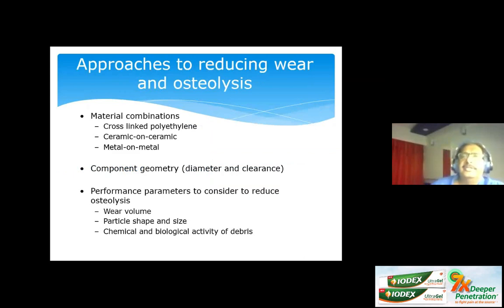So what are the approaches that we can use to reduce the wear and the osteolysis? First of all is the material combinations, whether we use cross-linked polyethylene, whether we use ceramic on ceramic. And earlier, that was also the rationale for metal on metal, which of course now has been put on the back burner for various reasons. Component geometry, in fact, which refers to diameter of the head and clearance, is important, and we will touch on that in a minute. Performance parameters that we consider to reduce osteolysis is the volume of wear, the size and shape of the particles, and how biologically active the debris is.